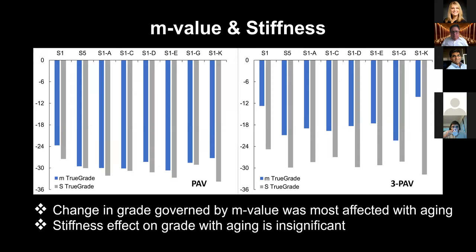Since the calculation for delta TC is the difference between the critical temperature of the creep stiffness minus the critical temperature of the creep rate, the sign on the delta TC, whether positive or negative, is determined by the creep stiffness, a positive delta TC, or by creep rate, a minus delta TC. As you can see by this graphic, after aging, the m-value was most affected by aging, and thus more negative delta TC values were seen after aging.